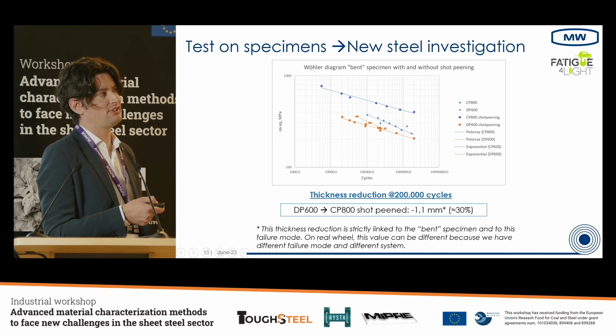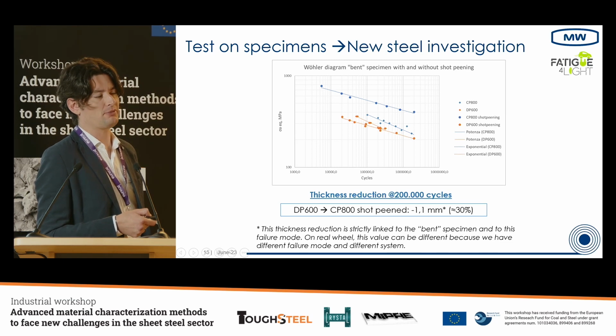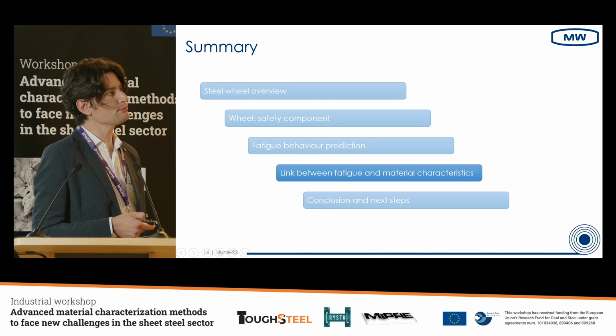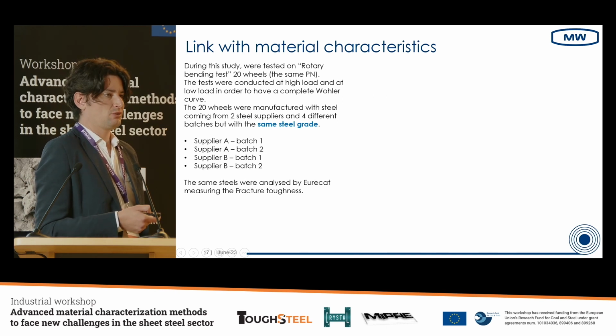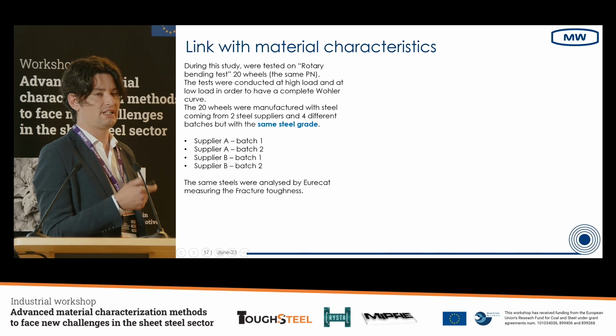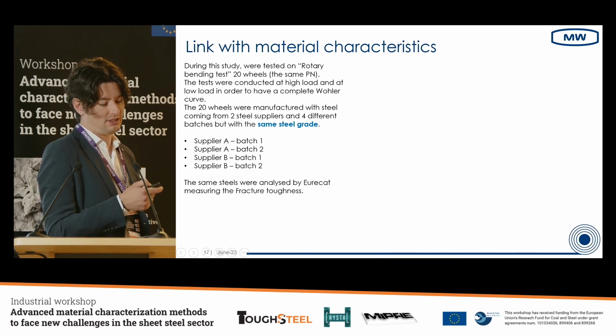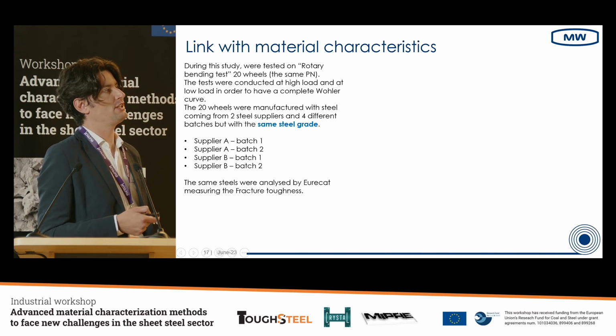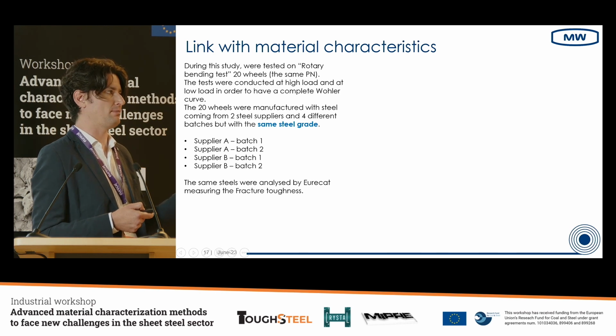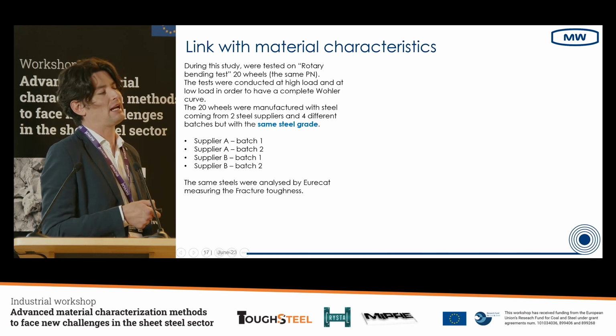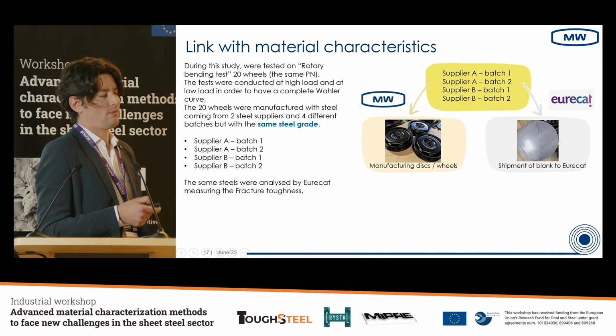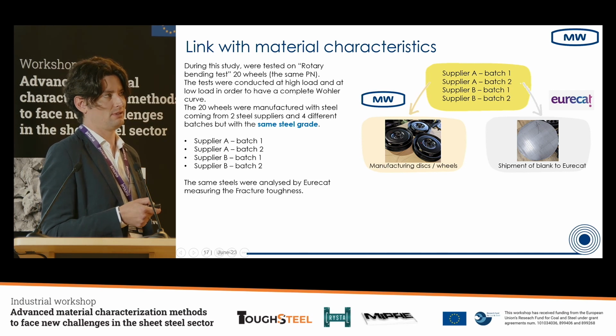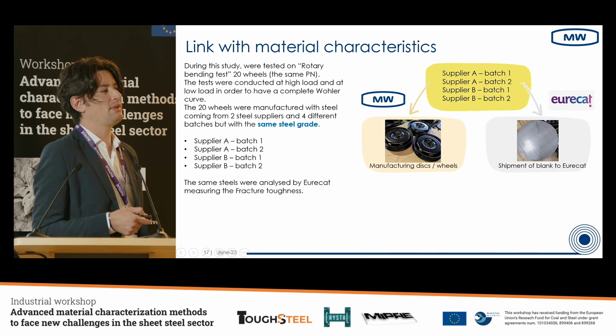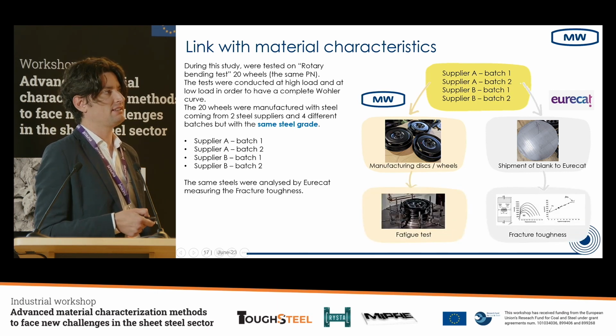And the first test that we did on the wheel, not on the bent specimen but on a real test, confirms this tendency. Okay, the last point is the link between fatigue and material characteristics. This is an activity that we did with Eurecat. So we identified one case study, one wheel, with the disc made in DP600. We identified 2 different suppliers of steel and 2 batches for each supplier. So in total, we have 4 different types of the same wheel. We produced the wheel with these 4 types of steel, and we sent the blank to Eurecat. MW made the test on fatigue, and Eurecat analyzed the fracture toughness.